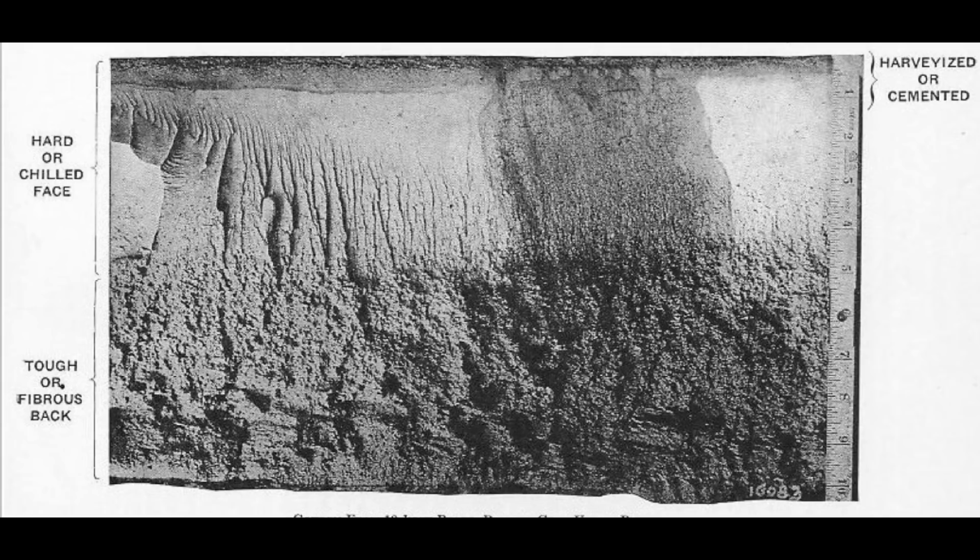In Harvey armour, this was done by literally stacking burning coals on top of one side of the plate and keeping them burning for ages. Later on, in Krupp armour, other methods were used, carbon-rich gases and such, to accelerate the process and get a more even spread. This obviously turns your basic steel into a high carbon steel on one side, and then once you've made that face high carbon steel, you then have to quench it relatively quickly.